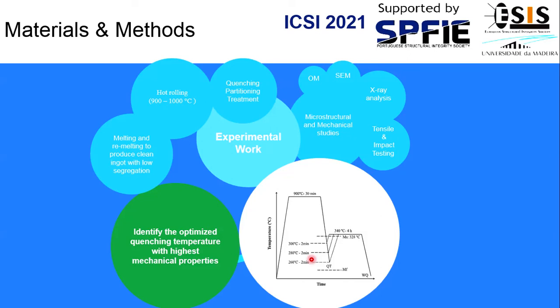These temperatures are 260 degrees Celsius, 280 degrees Celsius, and 300 degrees Celsius. And the samples were held for 2 minutes, and then the partitioning treatment was done at a temperature above martensite start. This temperature is above 240 degrees Celsius for 4 hours, and finally all samples were cooled in water.